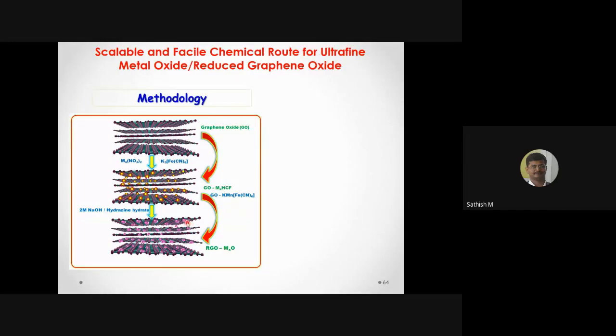Here the metal oxides are crystalline without any heat treatment. Generally, if you take a metal nitrate, some copper nitrate or iron nitrate, and you precipitate it, you will end up with amorphous material. When you heat it to 400 or 500 degrees, only then will you get crystalline. But in this case, we end up with a highly crystalline system without any heat treatment.